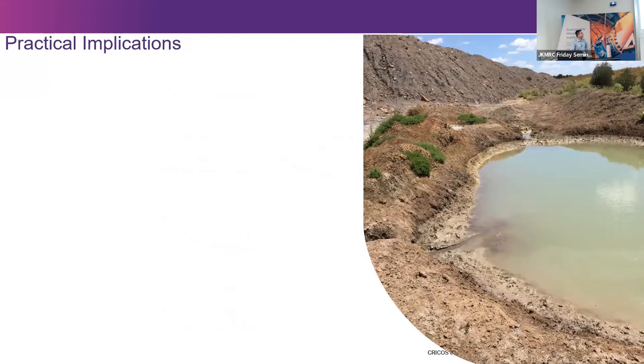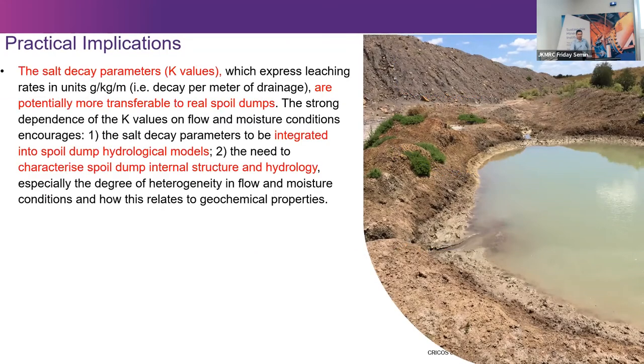And then the practical implications of this work were that the salt decay parameters, which express leaching rates in units of gram per kilogram per meter, that is decay per meter of drainage, are potentially more transferable to real spoil dumps. The strong dependence of K values on flow and moisture conditions encourages the salt decay parameters to be integrated into spoil dump hydrological models, and the need to characterize spoil dump internal structure and hydrology, especially the degree of heterogeneity in flow and moisture conditions and how this relates to geochemical properties. So that's one of the practical implications.